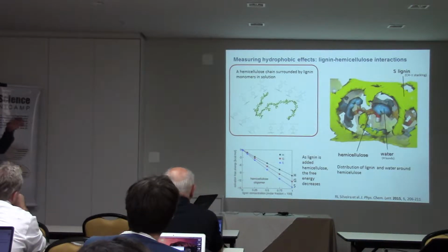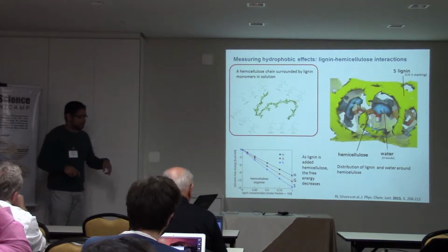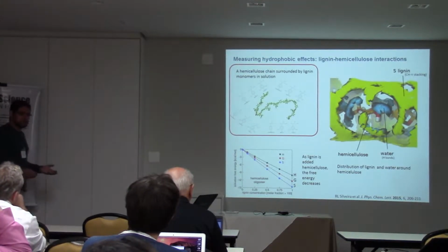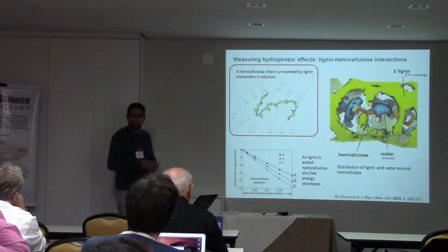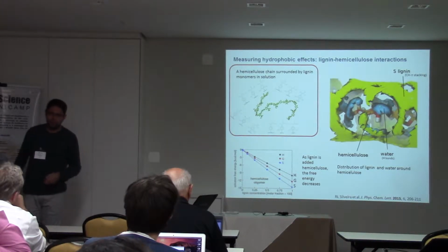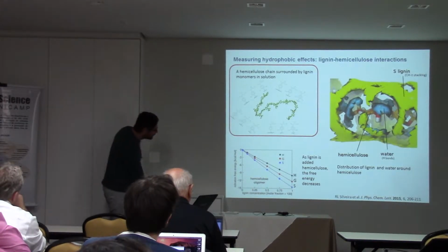So this also happens experimentally sometimes. Some genetic modification that increases the S lignin and reduces the H lignin or G lignin actually results in stronger cell walls. So they need more intense pre-treatments to break down the cell wall. And the opposite is true in some cases too. So that's why.